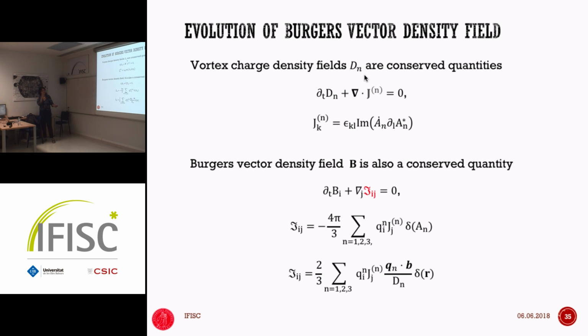All right, because these vortices in the amplitude expansion are topological defects, they satisfy a conservation law. They always come in pairs, they always annihilate in pairs. So there is this basic conservation law of the charge density field, with the current that is directly related to the evolution of the amplitude and some spatial derivative in this combination. Okay? So this is something that has been calculated by Mazenko. It's a technical calculation, but let's just say that it's a formula like this. We know it. Then how do we translate this for the Burgers vector?